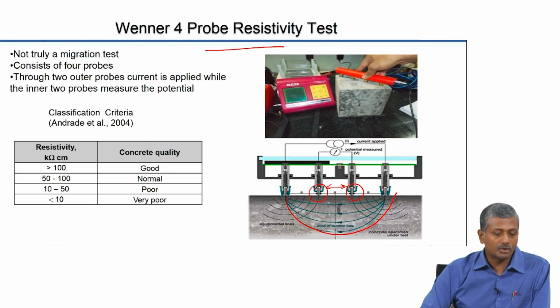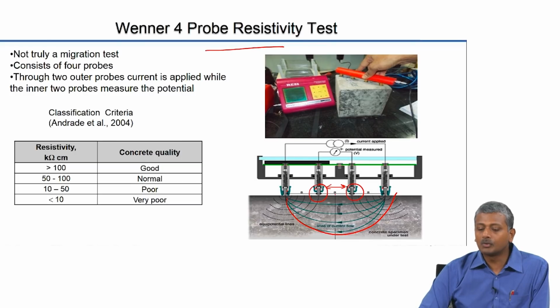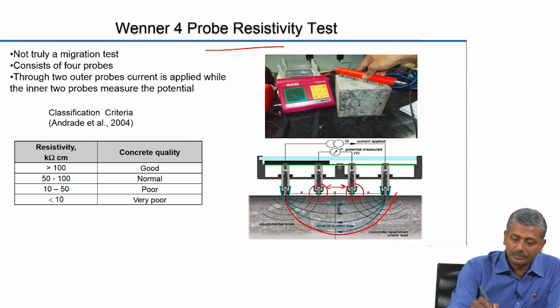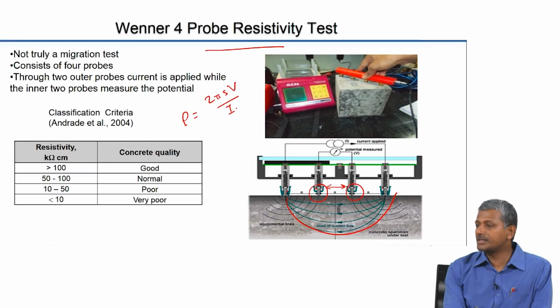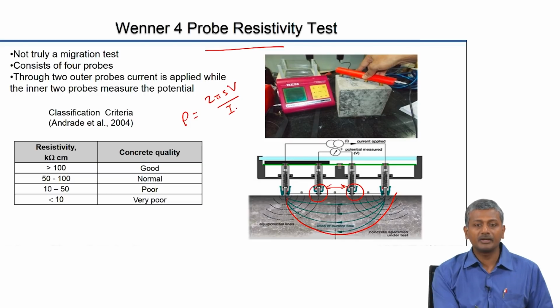You determine the potential drop across the inner probes and convert that potential drop to the resistivity rho, which is equal to 2 pi times spacing times the potential that is measured between the inner probes divided by the current that is passed in the system, 2 pi s v by I.